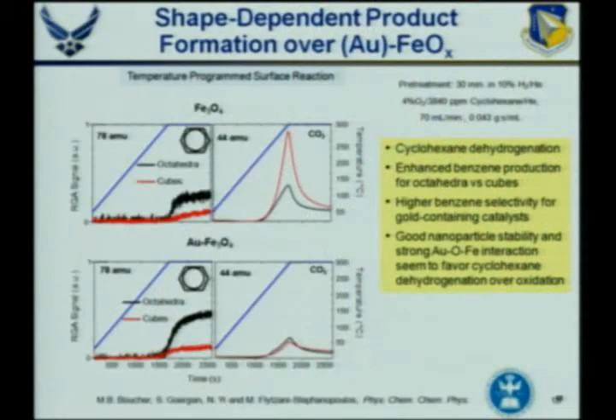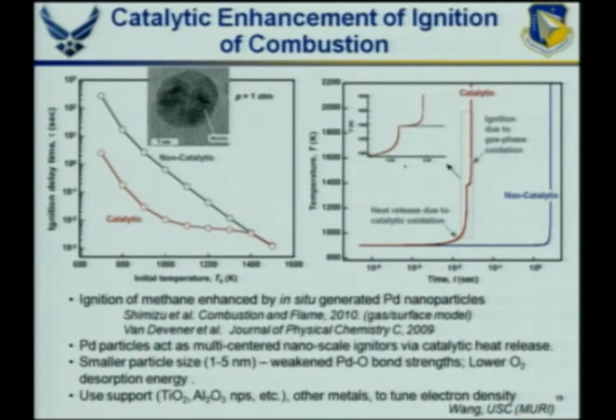Well, there are other ways that we can control catalysis. We'd like to control catalysis. As part of this, you see, again for cyclohexane dehydrogenation, in these iron oxide nanoparticles, you get different reactivity if the nanoparticles are octahedra versus cubes. And we can enhance that reactivity by putting in a gold atom. So you see much faster reactivity with octahedra versus cubes. So there are lots of different ways that we can control this reactivity.